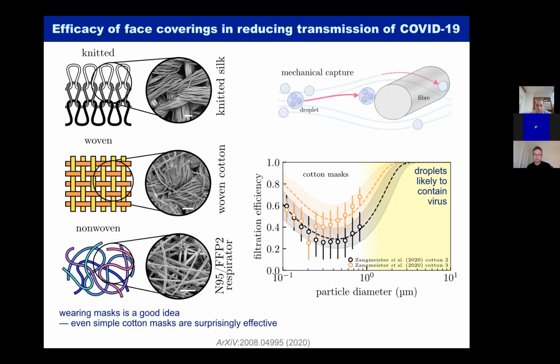Some of them are shown on the left of this slide, and the main results are shown in the bottom right of the slide. And the upshot is that almost anything within reason that you make a mask out of, be it cotton, be it a surgical mask, be it a fancy N95 mask, they will stop droplets larger than about a micron in size. It turns out those are the ones which are more likely to be containing significant amounts of virus, but there is a region of somewhat smaller droplets that the cotton masks, for example, are not very effective over.